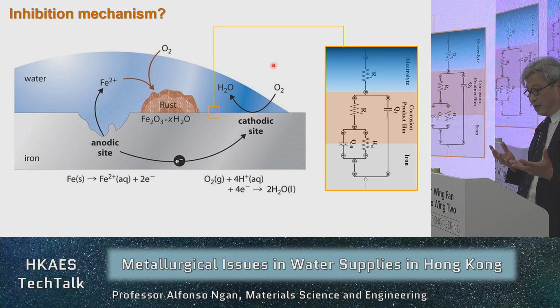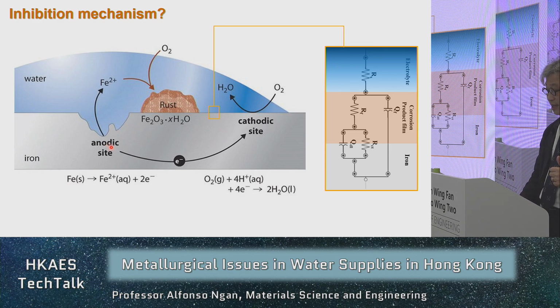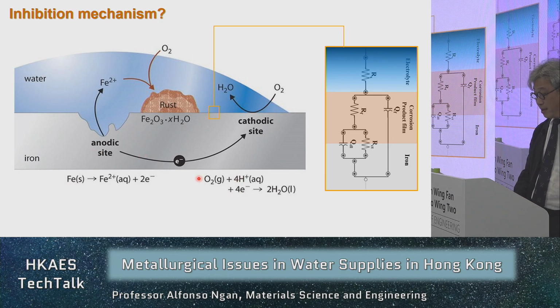What is the inhibition mechanism? So a very simple picture for corrosion of ferrous material is that there should be an anodic reaction. So for that, the iron will oxidize into iron 2+, and then losing 2 electrons. The 2 electrons will be fed into the cathodic site, where the cathodic reaction will happen. So typically that would involve converting oxygen into water by absorbing the electrons from the anodic site. Okay, and then the generated ions will then react with oxygen to form your rust.